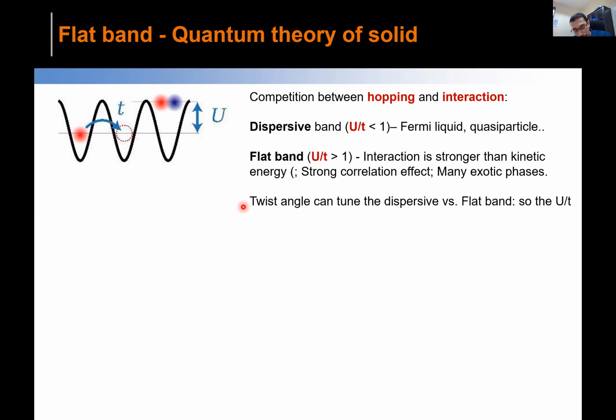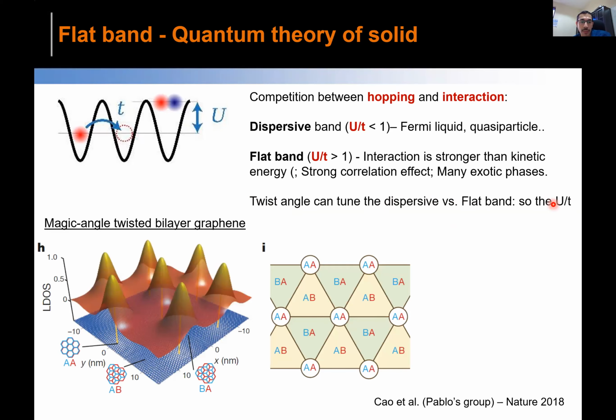Having said that, the important thing now is this twisted bilayer graphene. Here the twist angle is another tunable parameter which can control this dispersive versus flat band. For example, near the magic angle, as in the previous plot, the dispersion is almost dispersionless. As you go away from the magic angle, either below or higher, the band becomes dispersive. So you have a complete knob to control this parameter.